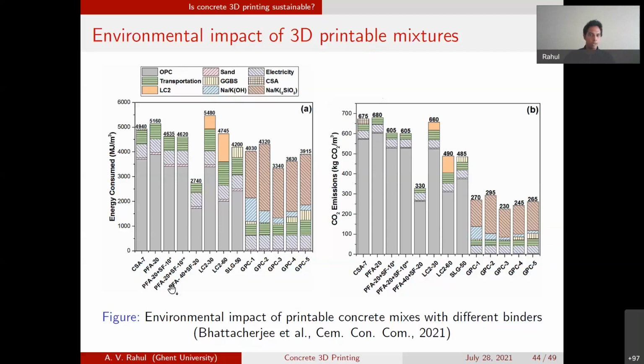Here you can see that there's calcium sulfoaluminate cement, there are mixes with fly ash, a silica fume fly ash blend, there's limestone calcined clay, which is also being talked of as a very green type of cement, and different types of geopolymer concrete as well. The energy consumed in making per meter cube of this material, and the carbon dioxide emission associated with per meter cube of this material, is shown in this figure. So this type of analysis allows us to choose which mixes are likely to create a lower environmental impact. So if you look here, this is likely to create a lower environmental impact during its production stage. That's important. Here we are talking about energy consumption and carbon emissions that occur during its production stage.